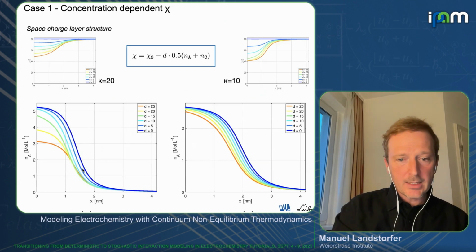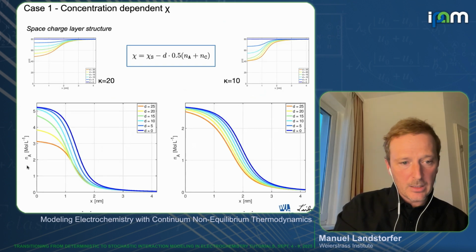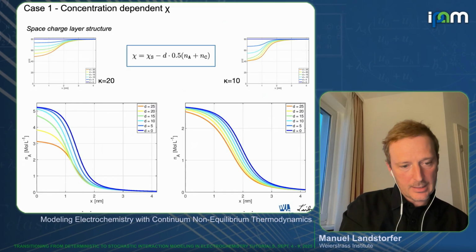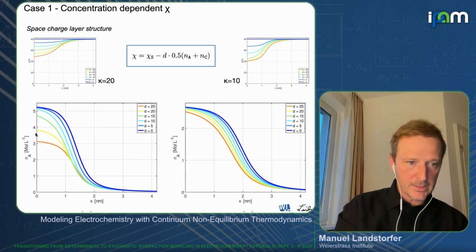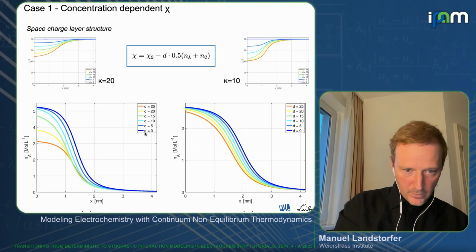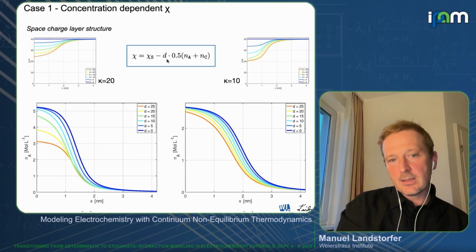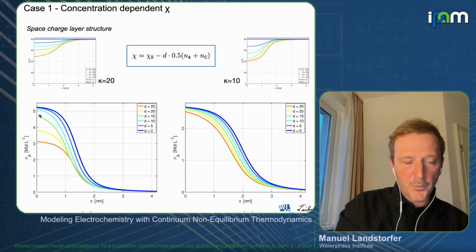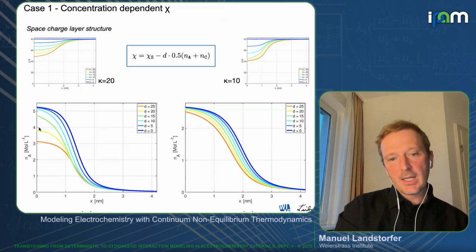In accordance with that, I will now show you what the concentration of anions in space looks like. Here at x0 is always the metal surface, and you can see that for increasing values of this dielectric decrement, the concentration necessarily has to decrease, again for large and smaller solvation number.